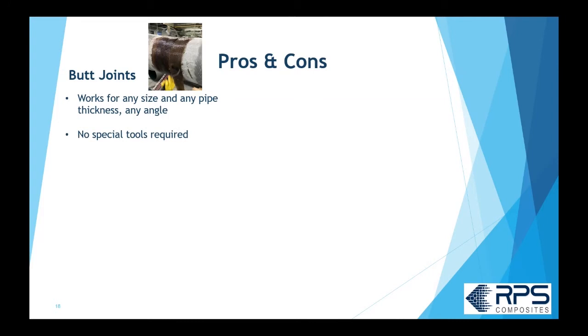There's no special tools required for a butt wrap joint. You just need a mini grinder and some basic tools, and that roller is about the only special tool you may want, but those are pretty commonly available. A butt joint will have better bending strength than an adhesive joint, and actually better than the pipe itself, because I have the full thickness of the pipe at the seam, and then I have a big thick laminate over top of it, so there's a lot of stiffness at that location.